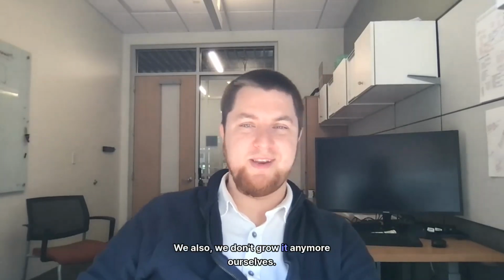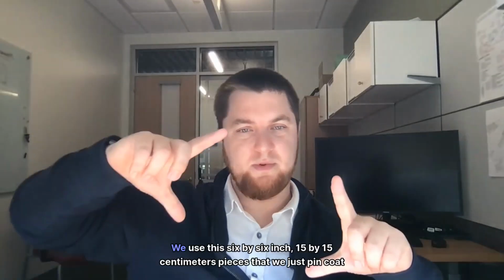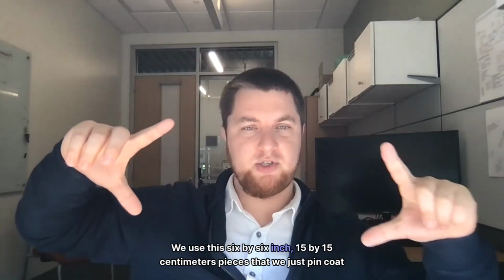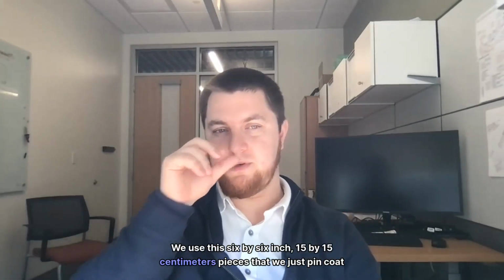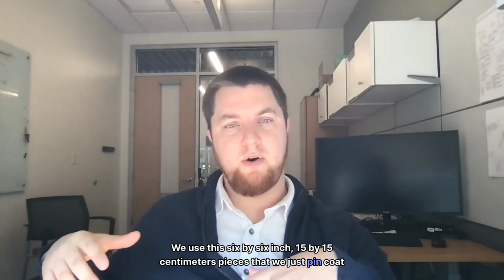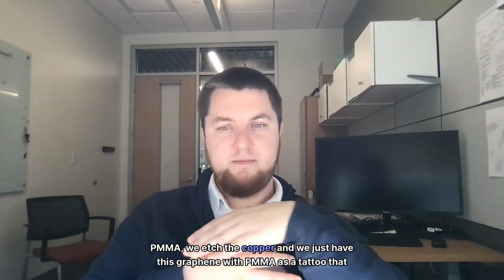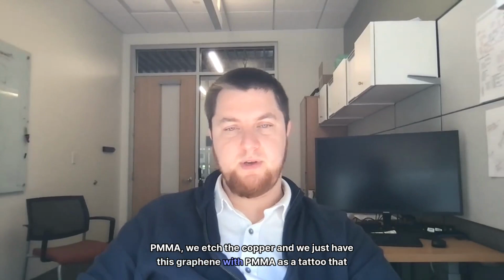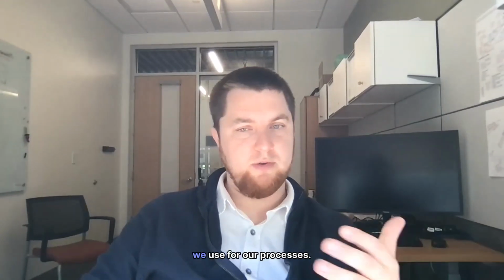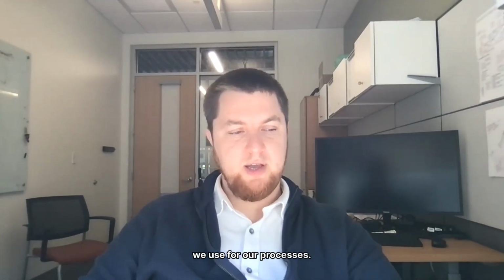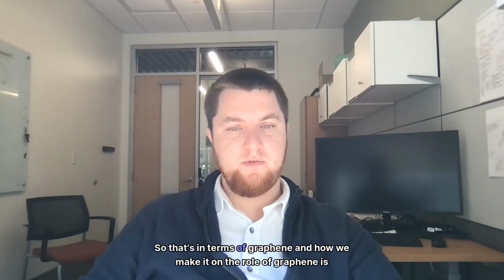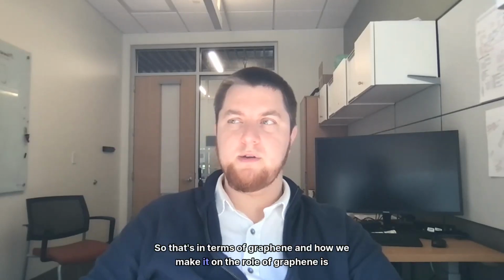We don't grow it anymore ourselves. We just buy it. We use 6x6 inch, 15x15 centimeter pieces that we spin coat with PMMA. We etch the copper, and we just have this graphene with PMMA as a tattoo that we use for our processes. So that's in terms of graphene and how we make it.